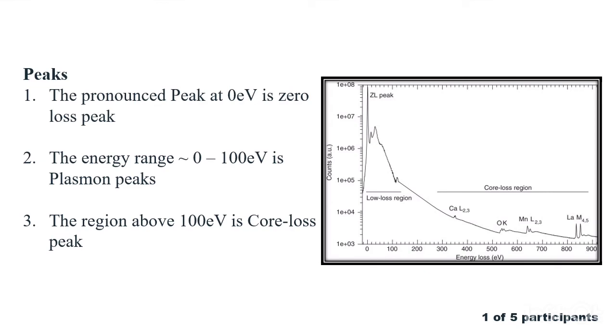This was a short and brief introduction about electron energy loss spectroscopy. If we think about why we use this technique, the answer is that we use this analysis to show that amorphous diamond consists of almost sp3 bonded carbon, which is close to crystalline diamond as compared with other highly sp3 bonded amorphous carbons. This was the reason why we use EELS, which I explained with a simple example.